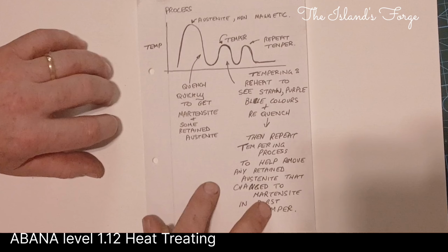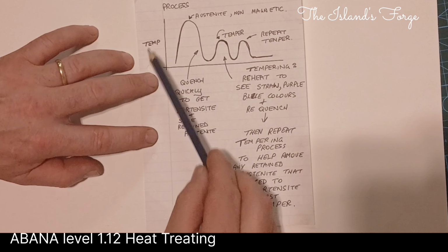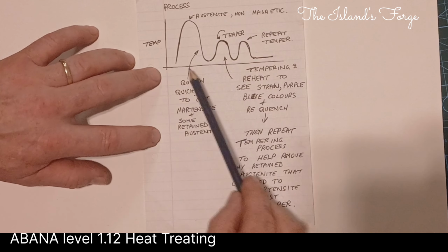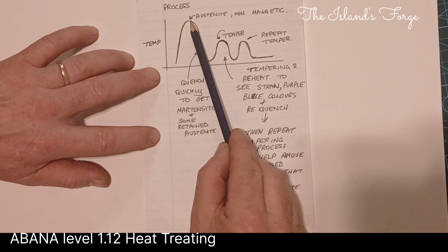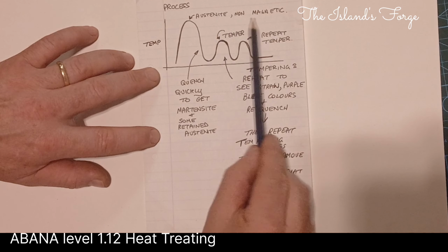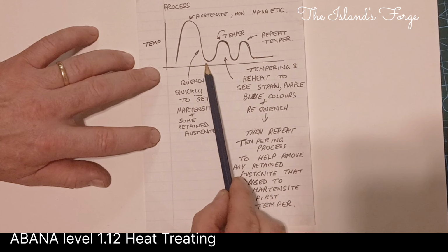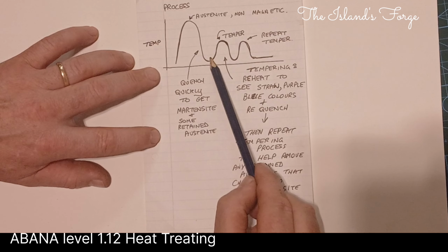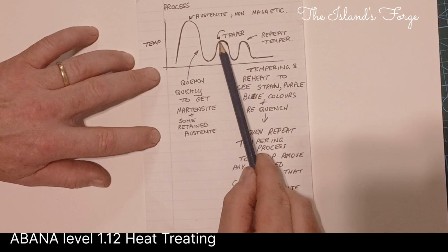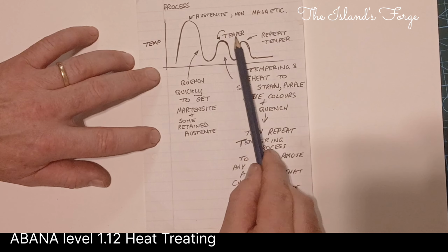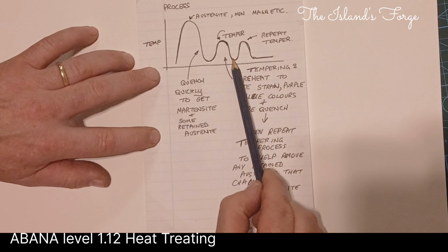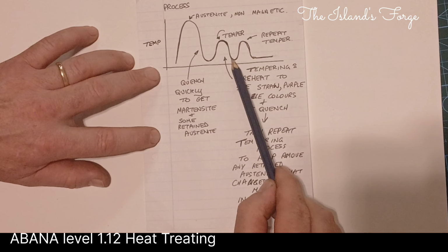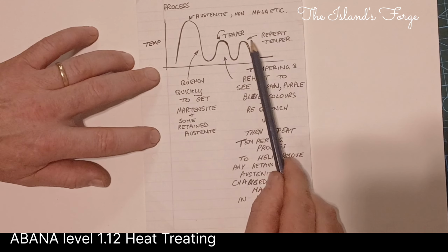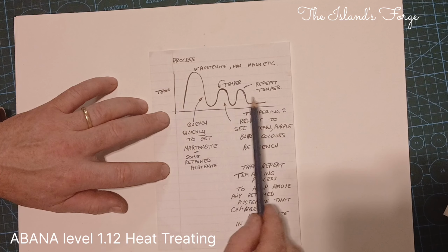To summarise that process again, in a chart, let's say this is the temperature line and this is time here. We bring up the temperature of the piece to non-magnetic, that's called the austenite. We quench quickly in the water and we get back down here to martensite. Then we bring it back up a certain amount into those straw, purple, blue colours. The different colours would give a different temper, and that tempers it. Quench. Traps that in. And then we temper a second time. Quench. So that's your hardening and tempering.